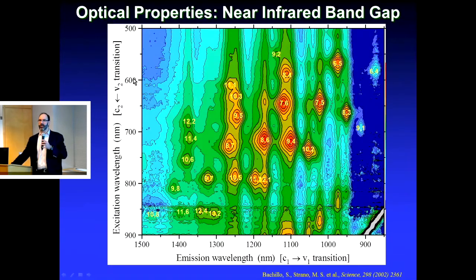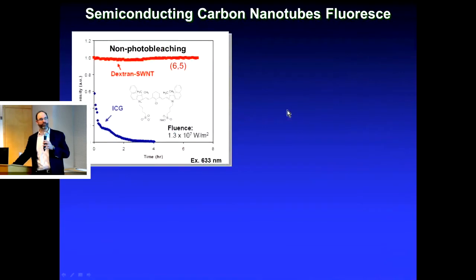So even though that sample had 40 different carbon nanotubes, I can actually do what's called an excitation profile. I can vary this laser pointer energy as it becomes resonant with different carbon nanotubes. I'll see fluorescent emission along this infrared wavelength. Okay, and so you can see even now there's a variety of different chemical species that we can use, all indexed by this chiral vector. Okay,